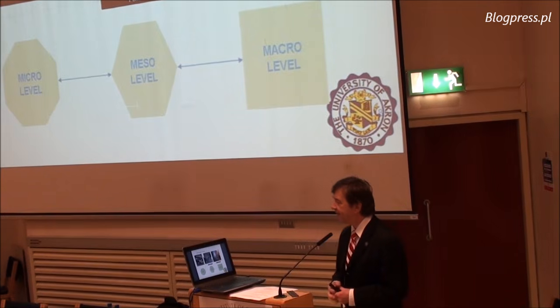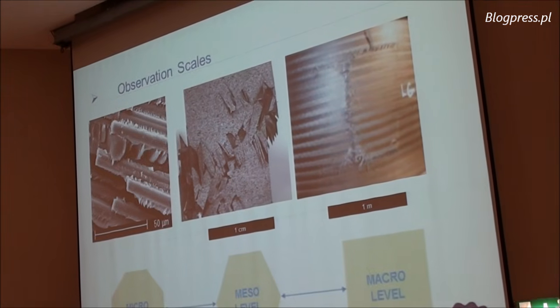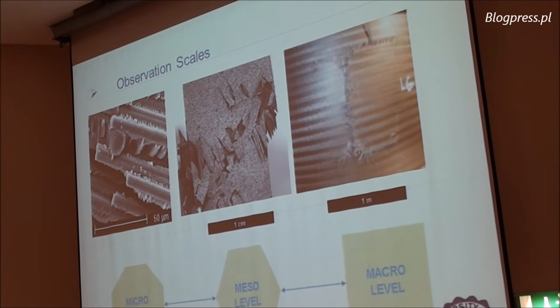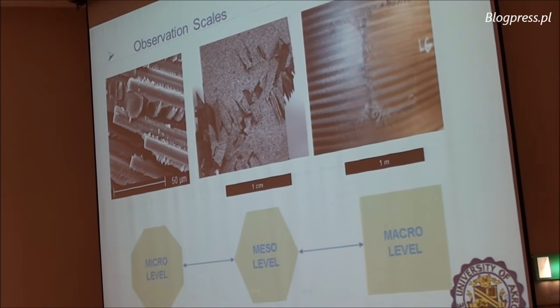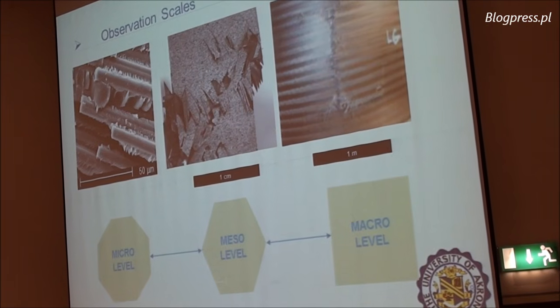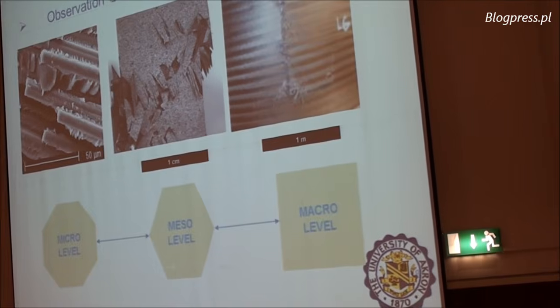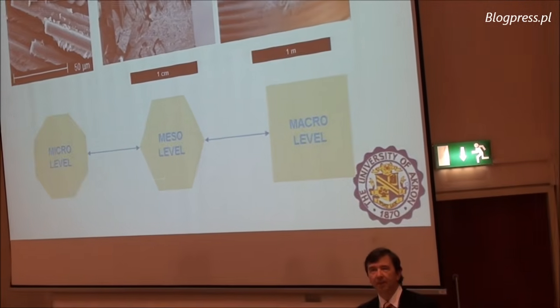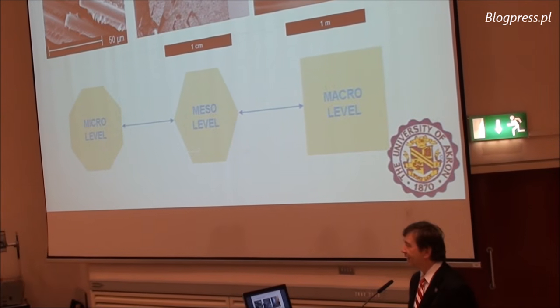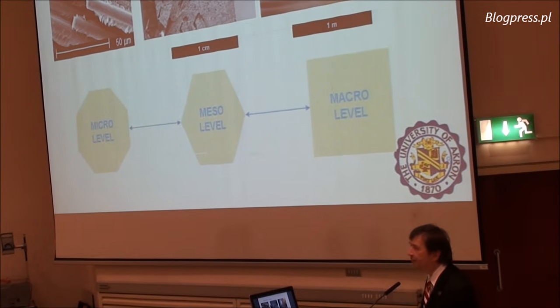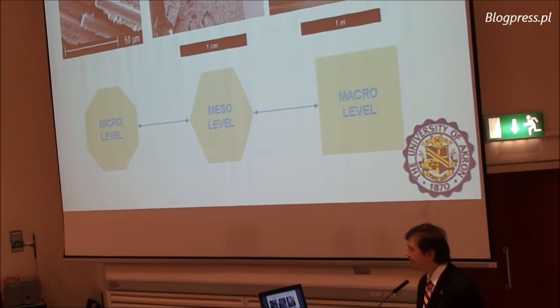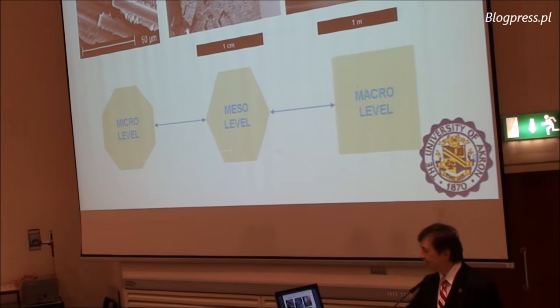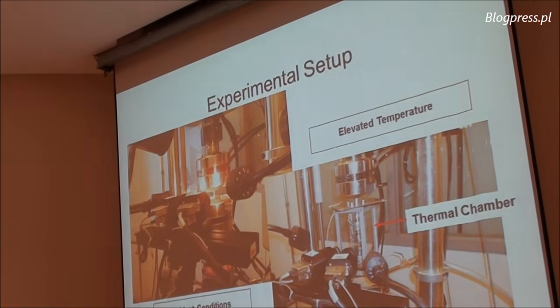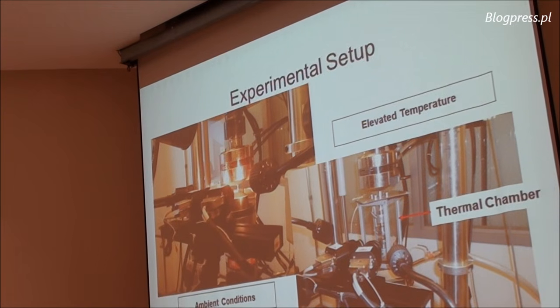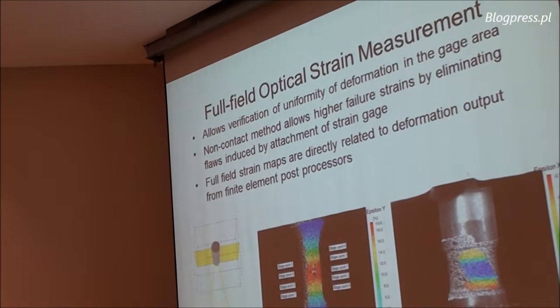Of course, when we test, you can see that at different levels, we will focus on different modes of failure. We can see at the micromechanical level, the adhesive or cohesive fracture of the material itself. We can see from the sample level the tension results, which looks like shear, and from the structural level we can see the damage due to application of the internal pressure, which makes the crack driven by the structure geometry of cylindrical structure itself.